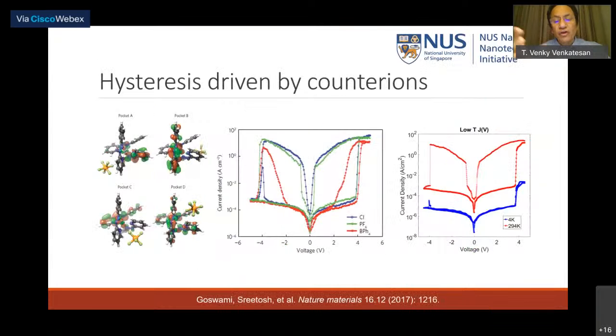But we also get a hysteresis, and where is that coming from? The hysteresis has to do with the counter ion. Remember I told you there's a companion ion that sits around. These are like PF6 molecules in this case, and this counter ion sits in very well-defined spatial coordinates right next to the molecule. So when I change the redox state of the molecule, the counter ion will move to a slightly different spatial pocket, and that pocket gives it inertia. So when I turn the voltage down, because of the inertia of the molecular system, I get a hysteresis here.